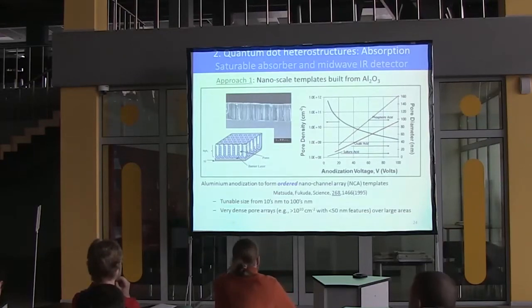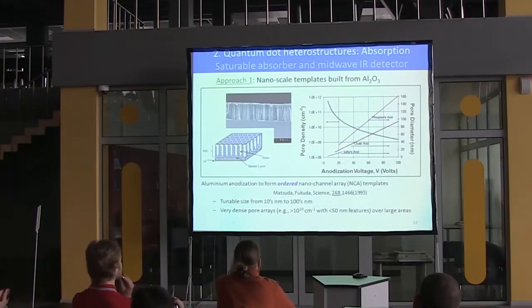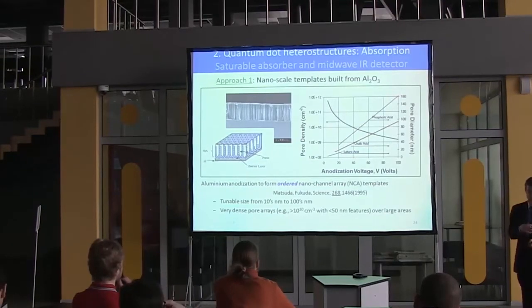Well, how much controllability can I have? That's shown in this diagram. By changing the anodization voltage, and also changing the electrolyte I use from sulfuric to oxalate or phosphoric acid, I can adjust the pore dimensions from anywhere like 10 nanometers in size, tiny, tiny holes, all the way up to hundreds of nanometers. And of course the pore density would go appropriately because the structure is a hexagonal kind of close-packed structure.